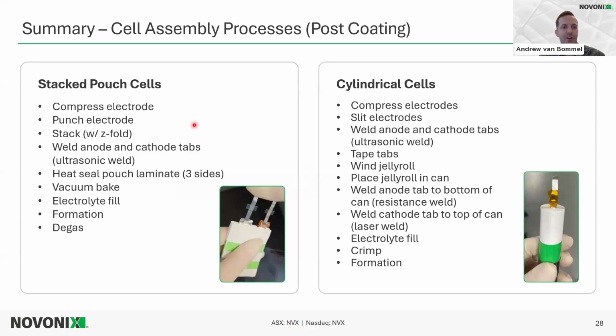So just to summarize for today, this is the cell assembly process post-coating. If you want to see more details about the mixing and the coating process, that would be in our previous webinar. So in terms of stacked pouch cells, we initially compress the electrode. We punch the electrode, and we have that 8-electrode punch for the smaller format stack cells that we make. That stack is done with a Z fold with the one separator roll on the stacker, which Z folds between the anodes and the cathodes.